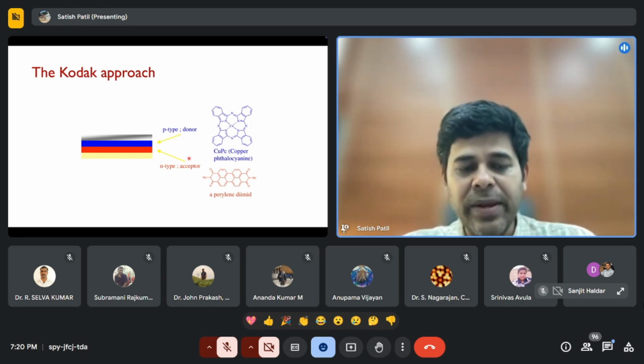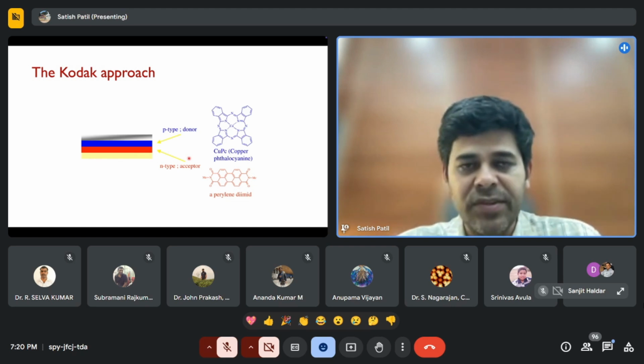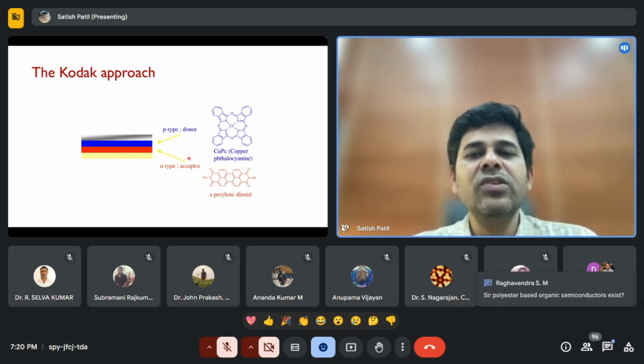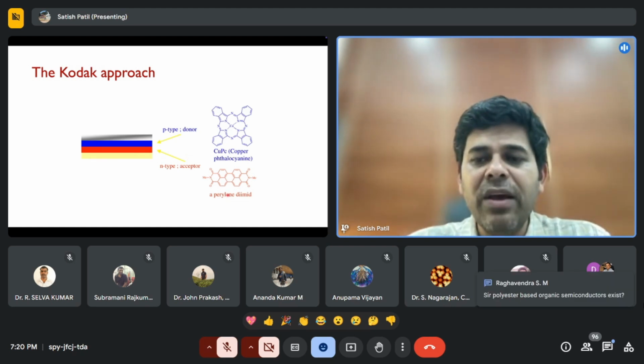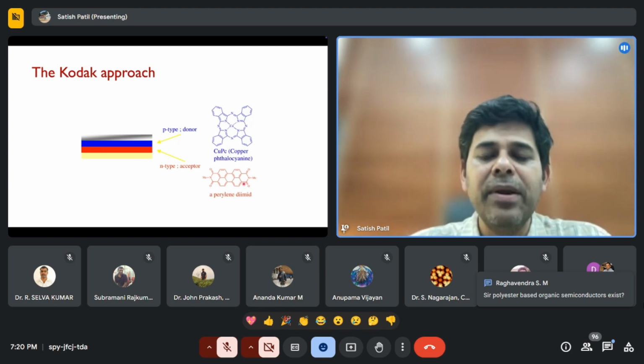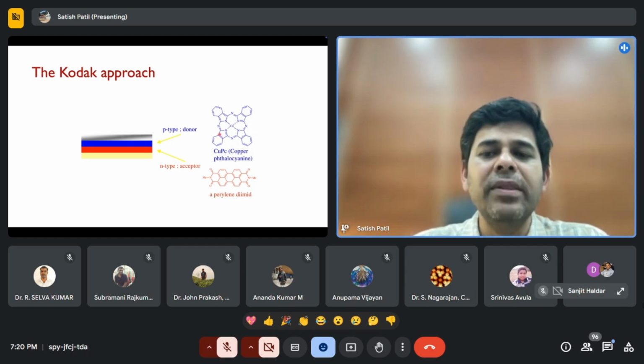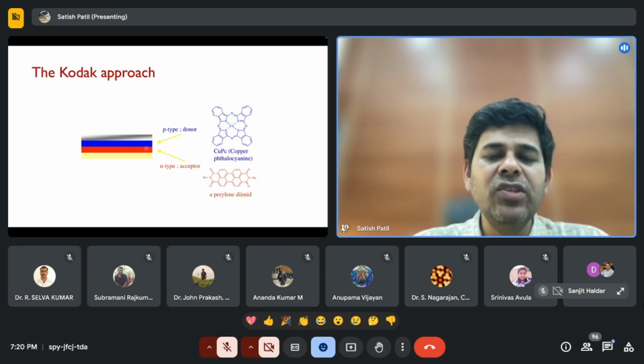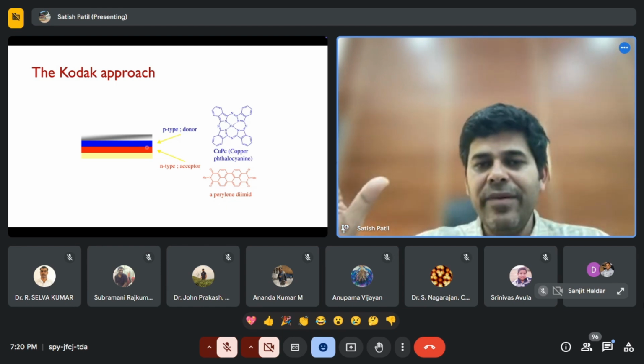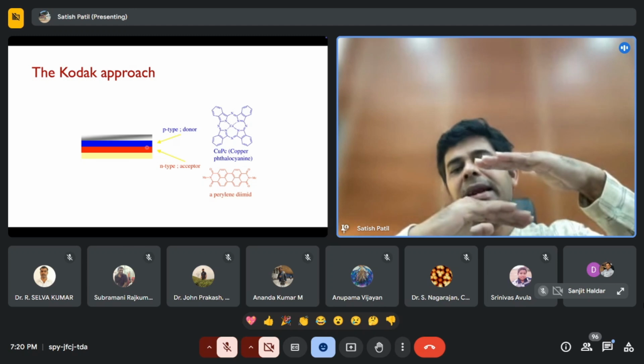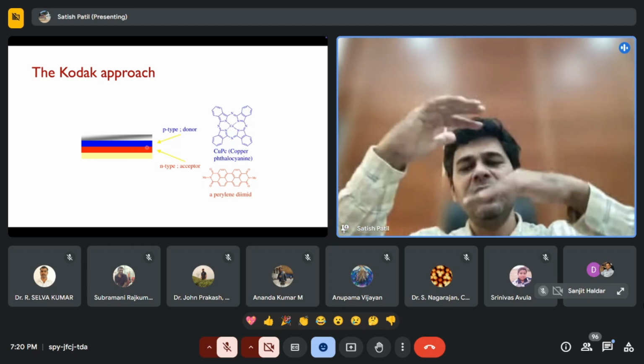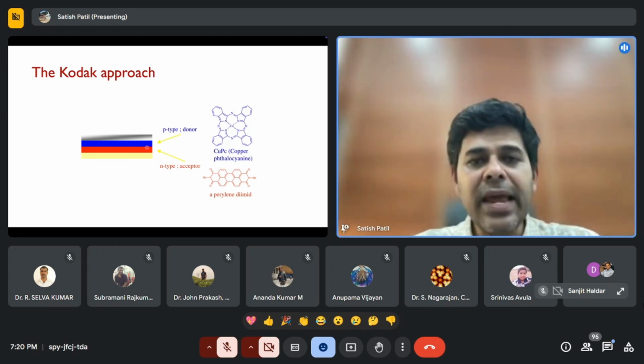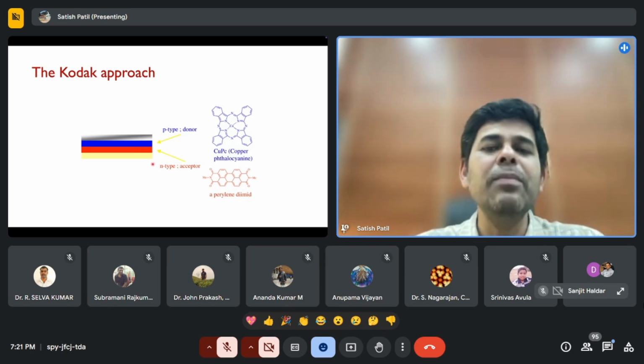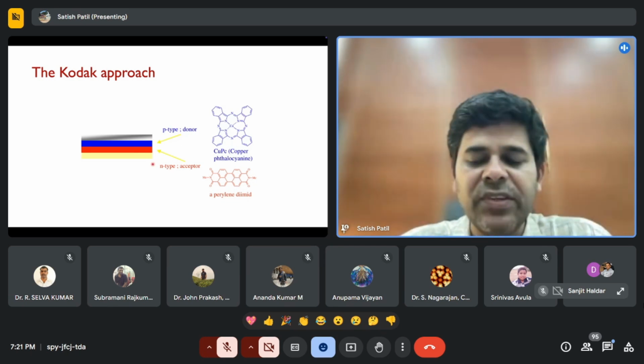What is the approach people have taken to make solar cells? The first approach is called the Kodak approach, where we have perylene diimide, an N-type material, an electron carrier, and the hole carrier is copper phthalocyanine. So in the Kodak approach, they use these two separate layers, a P-type semiconductor and an N-type semiconductor, and they sandwich them between two electrodes. And then the Kodak approach gave some efficiency. That was a 1% efficiency.